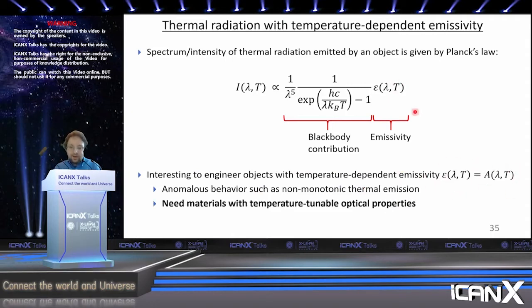And in that case, you have a very strange situation where your temperature dependence comes in not only in the blackbody contribution over here, but also in your emissivity, which becomes temperature dependent. And so you can imagine situations that are very anomalous. Like for example, maybe this term goes up with temperature, but this term goes down with temperature. And what does that mean for the total thermal radiation that is actually being emitted from this kind of object?